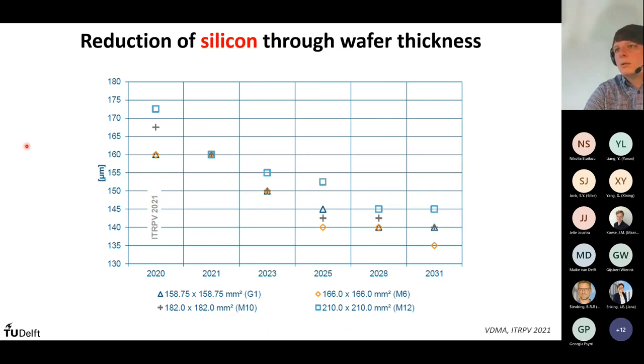Second is silicon, and we have reduced the use of silicon. So 10 years ago, we had wafer thicknesses of about 300 micron, and now it's about half of that. And we try to shave another 20 to 30 micrometers off that. The difficulty is that at 100 micrometers, it becomes really tough to handle the cells without breaking. So it's really a mechanical issue during production and during the lifetime of PV. But it's a main driver in cost.